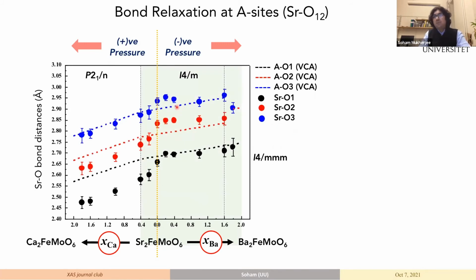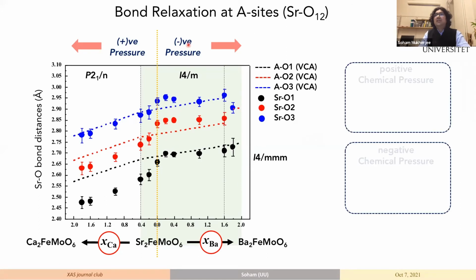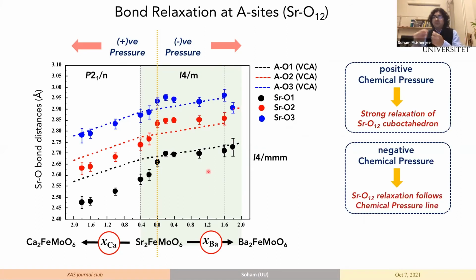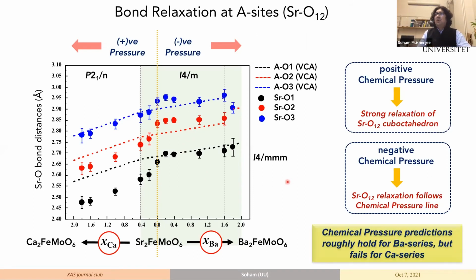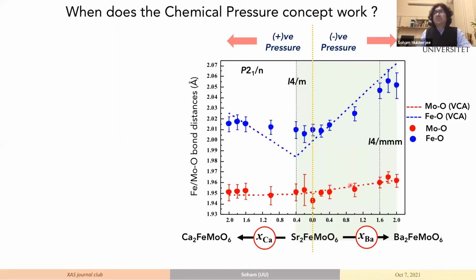Now we have the opposite trend. We have a stronger relaxation of the strontium-oxygen cuboctahedra on the positive pressure side, and a lower relaxation on the negative pressure side. So the A site and the B site respond in very different ways when we explore the positive pressure regime and the negative pressure regime. So we can see from comparing these two slides that the chemical pressure predictions roughly hold for the barium series, but it fails for the calcium series. So why? Now we want to identify when exactly the chemical pressure concept works.